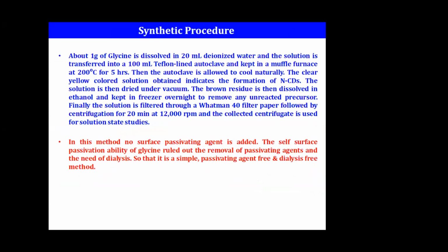So this is how we have looked at this material. Now, how do we synthesize this material? We take glycine as the raw source material, and then autoclave it in a Teflon-lined autoclave in a muffle furnace.